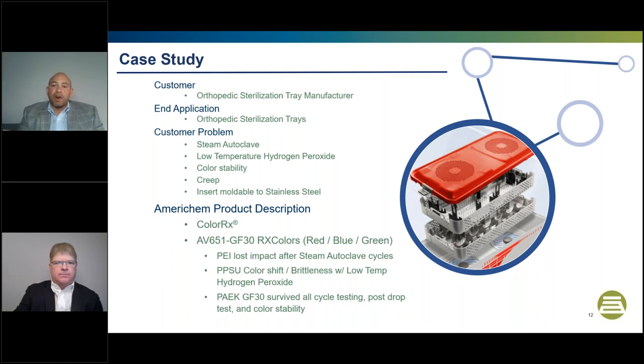So now we have the polymer set. You can see the part in red there on top. But then later on, the OEM wanted a stiffer product. So when you're talking stiffness, you're going to talk glass fiber. So we added 30% glass fiber to the product, and then it went to the molder, and we followed it to the molder, provided some molding assistance, and helped them to bury the glass.